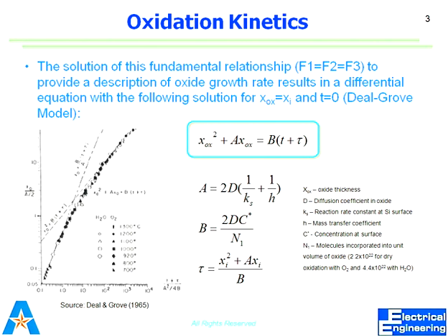If it does not have the initial oxide layer, tau would be equal to 0. And if there is some, let's suppose that in order to grow this native oxide it takes maybe 1 millisecond. So I'll have to put tau equal to 1 millisecond, assuming that 1 millisecond has already passed. So tau is the time displacement needed to account for the initial oxide layer.